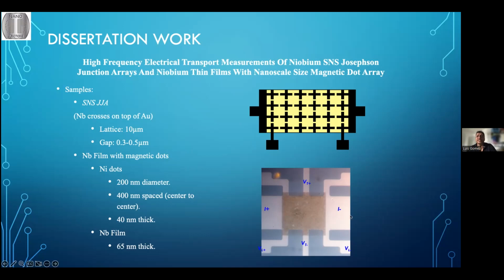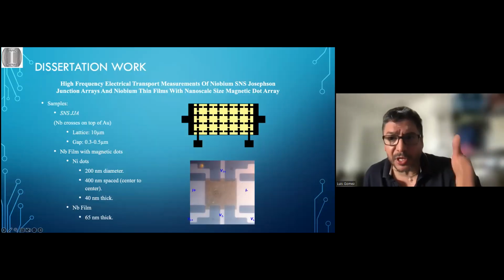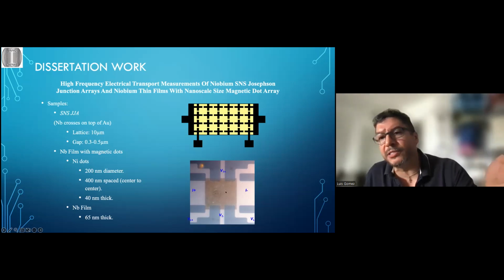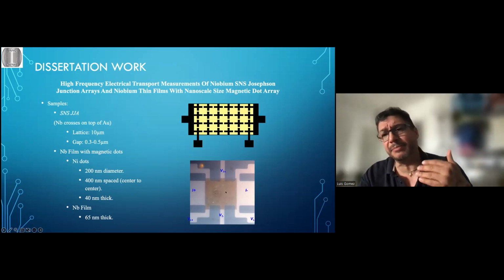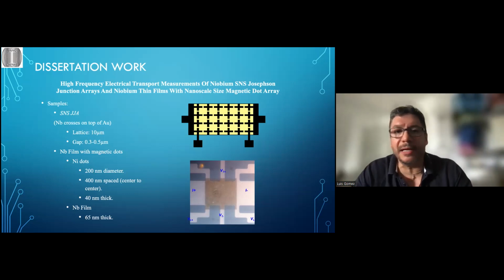On the other sample it is the same. We have a central channel for sending current, and we have many leads, so you can use this lead and this lead to measure the voltage. This will be a longitudinal voltage, but we also have these leads here that we can use to measure the transverse voltage. So this is also interesting. I did some experiments measuring the Hall voltage or the transverse voltage in the presence of an external magnetic field, a perpendicular magnetic field. And if you remember, I mentioned these are nickel dots. So they are magnetic. So I could magnetize them or randomly assign a magnetization to each one of the dots. And that also shows very interesting results.